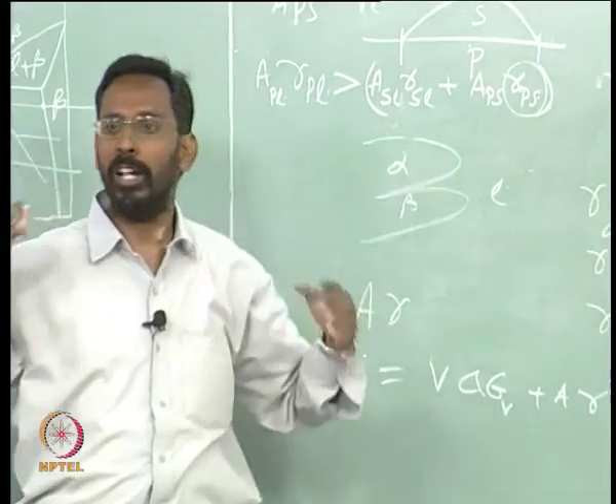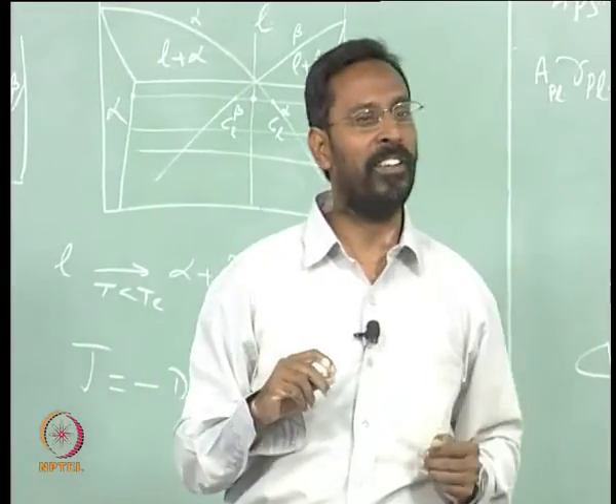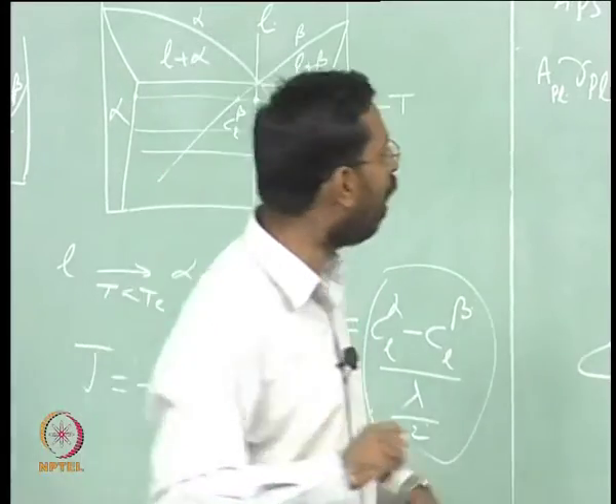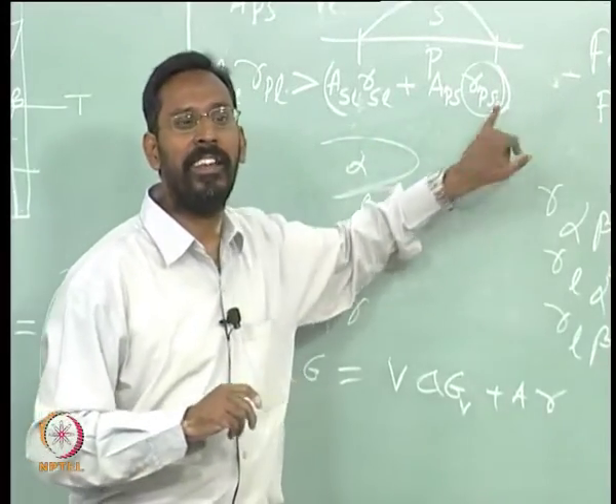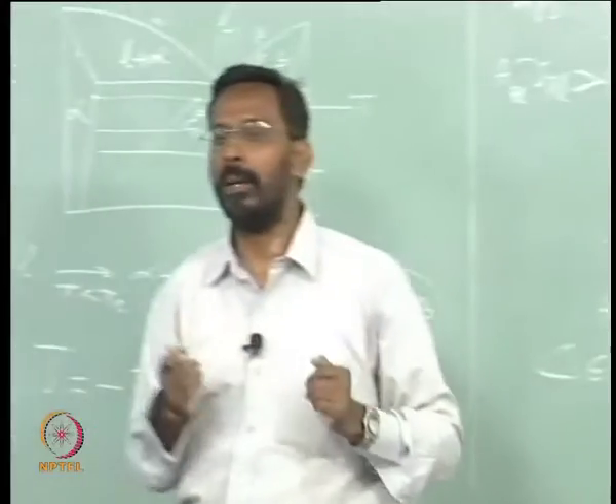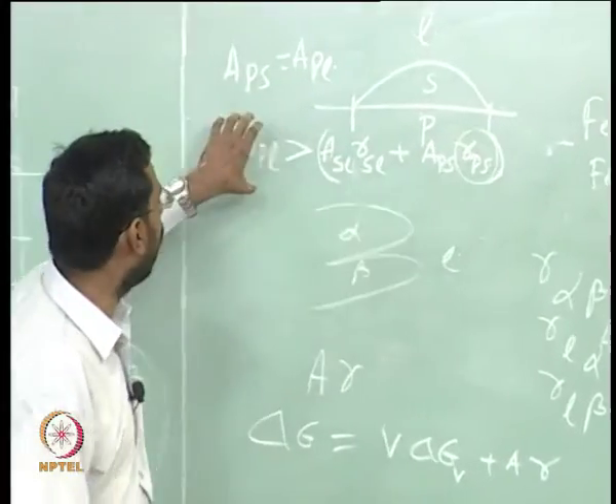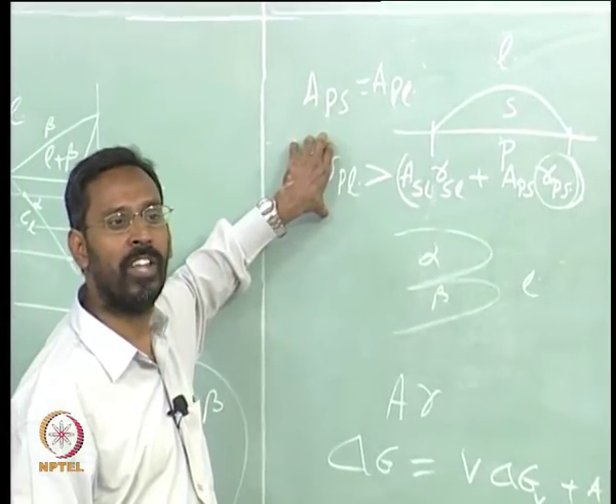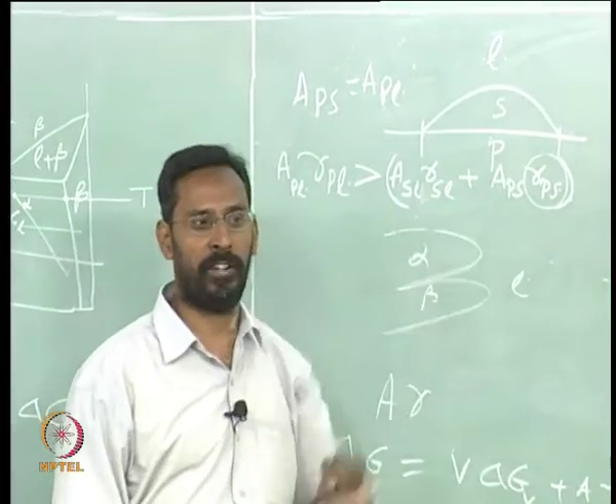That is why we talk in terms of coherent interfaces, semi-coherent interfaces - all that comes from lattice parameter compatibility. When this mismatch is much smaller, so that compatibility is satisfied, only then you have nucleation.